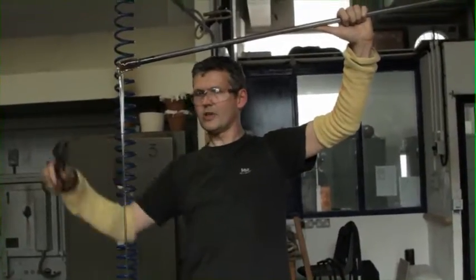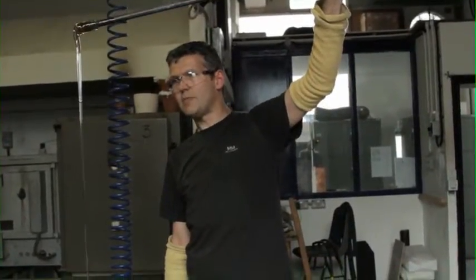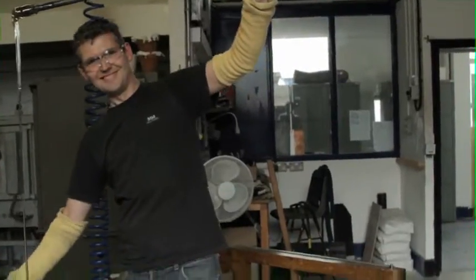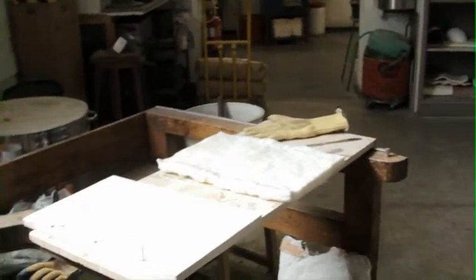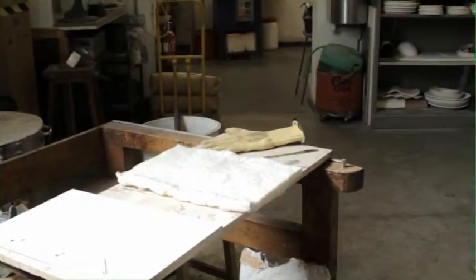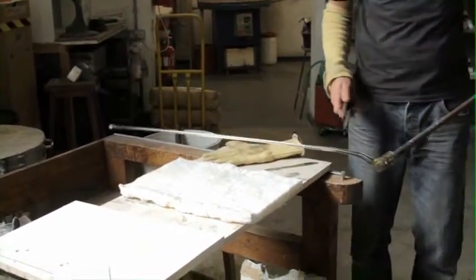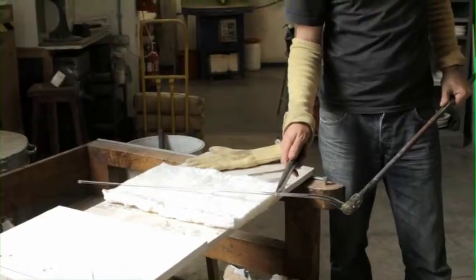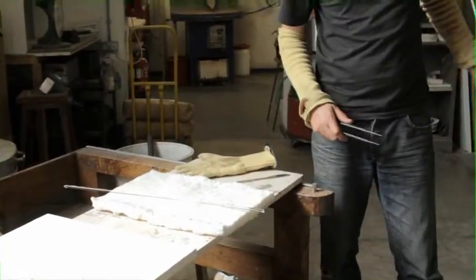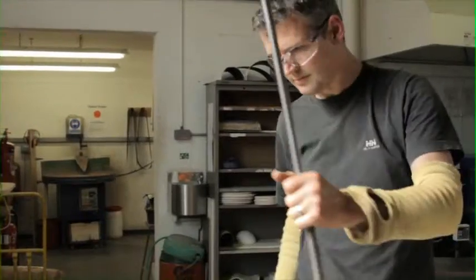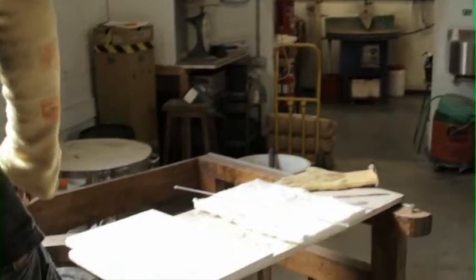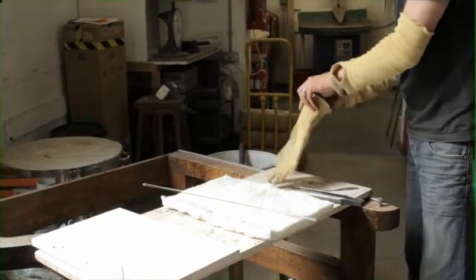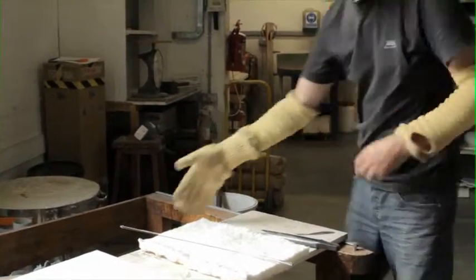so I decided to try a cane test to determine the softening point and therefore the safe annealing temperature of the glass. The cane is placed in an annealing oven, leaning at an angle of 45 degrees against the side wall. When it begins to bend in the oven, it gives us a softening point from which we can work out the annealing temperature. I was surprised that I could easily handle the glass at 1200 degrees C, which suggests a working temperature of just under that, about 1180 degrees C. Because of this, I guessed an annealing temperature of about 520 degrees C.